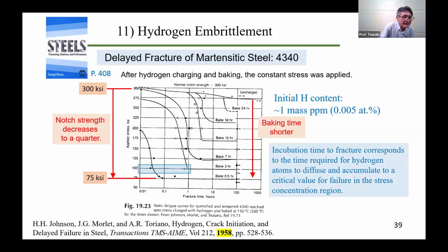Since there is an incubation time before failure, this fracture was named delayed fracture. It had been discussed that the incubation time to fracture corresponds to the time required for hydrogen atoms to diffuse and accumulate to a critical value for a failure in the stress concentration region at the notch root.